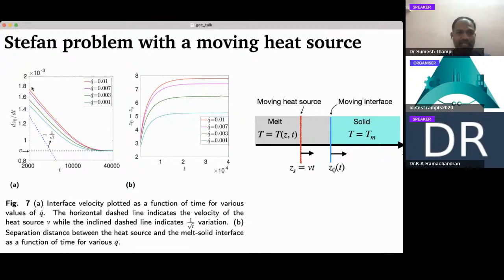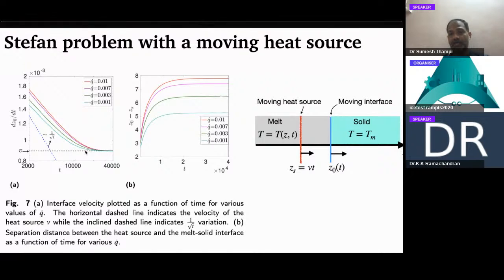So that's what happens, and that is how the system reaches the steady state. You can also see that there are different curves that I have plotted. They correspond to different amounts of heat that you are giving. As you go from blue to red, you are giving more and more heat into the system. When you are giving more and more heat into the system, initially the velocity of the interface will be larger, as you're seeing here, but all of them finally reach the same velocity as that of the heat source. So this phenomenon of the interface moving along with the velocity of the heat source, irrespective of the amount of heat that you give, is again a common, or universal, thing of this system.